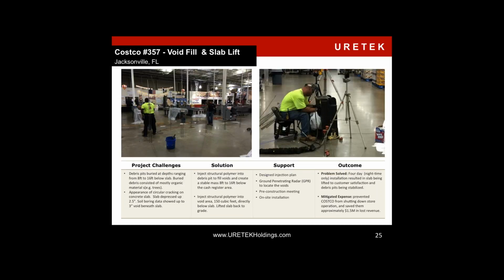Down in Jacksonville, Florida, Costco had an issue. They had post-construction settlement. The reason is there was buried debris, organic materials, trees, what have you. As those decompose and break down, you have settlement. They were having circular cracking areas on their concrete floors and settlement. So URETEK was commissioned to come in and do some GPR, ground penetrating radar, to determine where those voids were and the extent of them as far as the surface area.